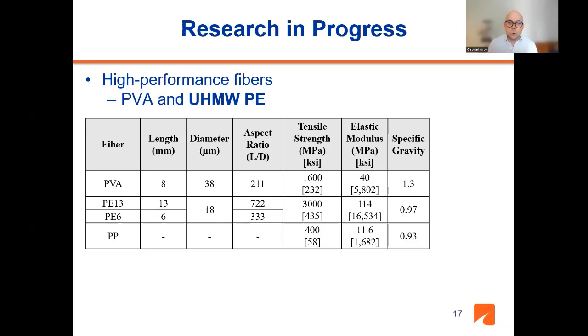Also, I have in the last row the properties of conventional polypropylene fiber, just as a comparison. As you can see, these fibers that we use are much stronger than the polypropylene fiber, stiffer than the polypropylene fiber. And this is important because usually these mortars that are used in the field to do this invert repair, centrifugally sprayed repairs use polypropylene fibers, and these fibers cannot give you the performance that you need for ECC. There are some special types of polypropylene fibers, specifically high tenacity polypropylene fibers that have been used in ECCs, but these are not the ones that are often used in the field.